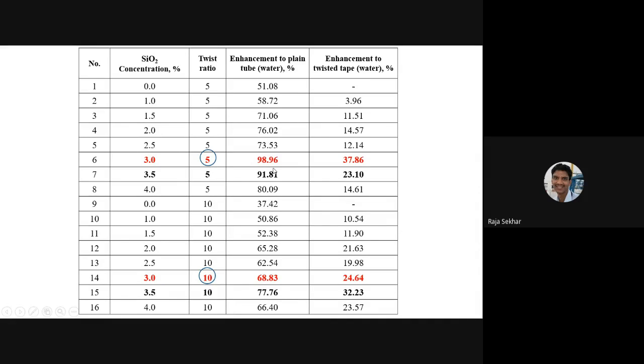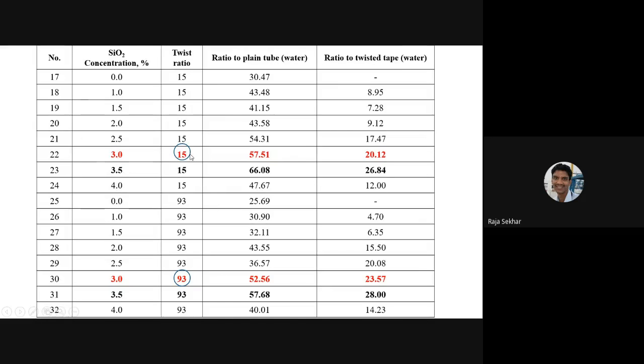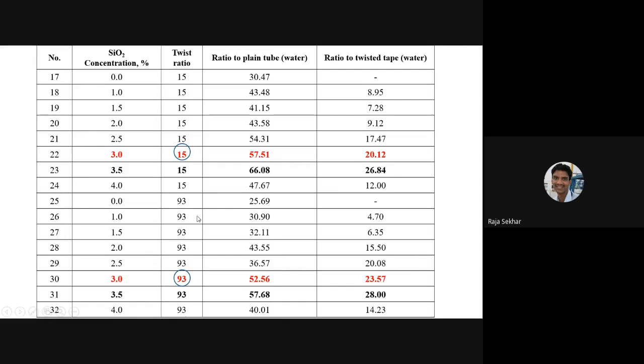This is for 5. This is the enhancement ratio. So that means for lower twist you are getting better enhancements. So for 5 it is 98 and for 10 it is 68. If you look at 15 and 93 also, it is somewhat reduced. So here it is 98, 68, and it is 57 and 52. So the more the twist ratio, the enhancement ratio is reduced. So you have to go for lower twist ratios and up to 3% of SiO2 concentration, you are getting better